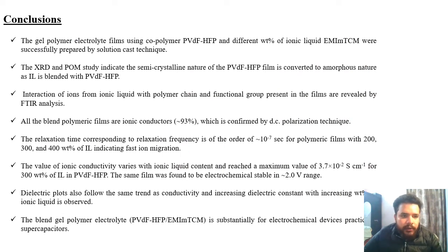So from here I have concluded that the gel polymer electrolyte films prepared using the copolymer PVDF-HFP and different weight percent of the ionic liquid EMIM TCM were successfully prepared by the solution cast technique. The XRD and POM studies indicate the semi-crystalline nature of the PVDF-HFP film, which is converted to amorphous nature when ionic liquid is added to it. The interaction of ions from the ionic liquid with the polymer chain and functional groups present in the films is revealed by the FTIR analysis. And all the polymeric films have ionic charge carriers in major amount, equal to 93%, which is confirmed by the DC polarization technique.